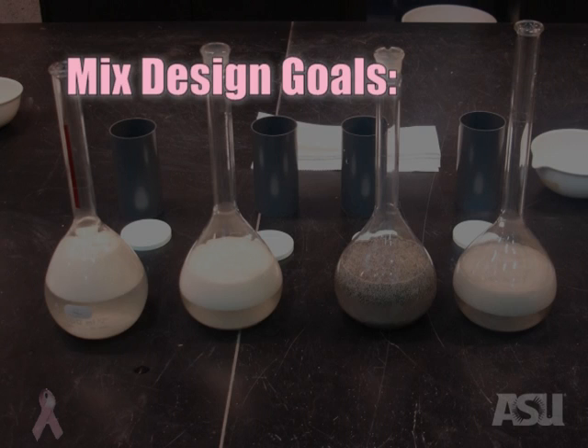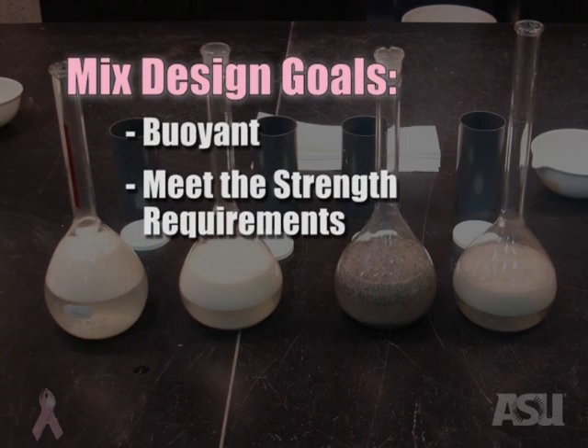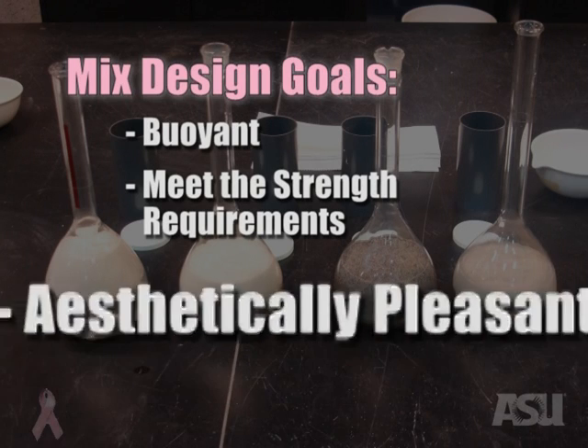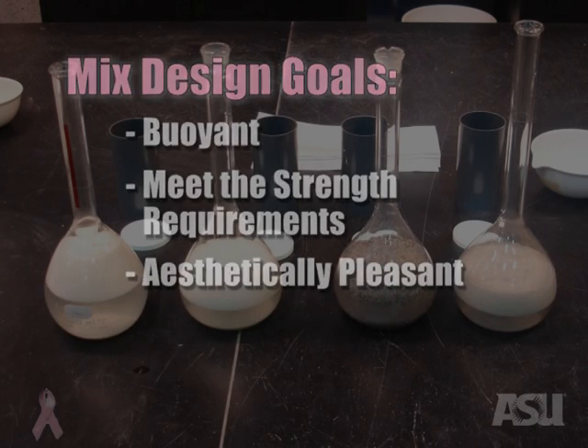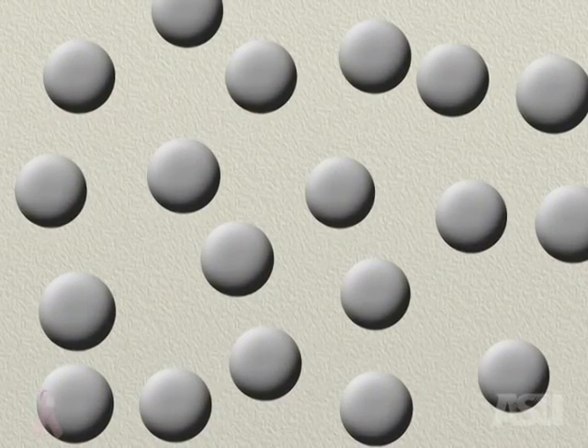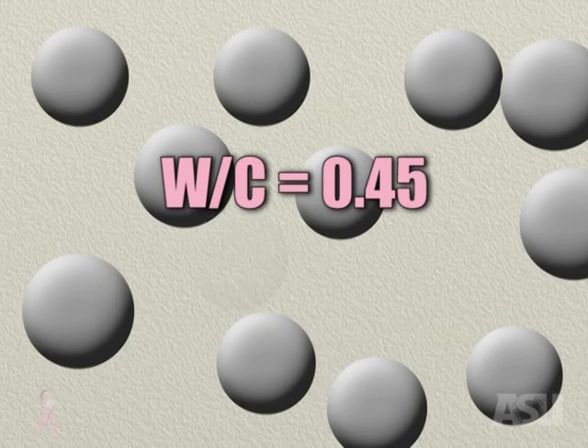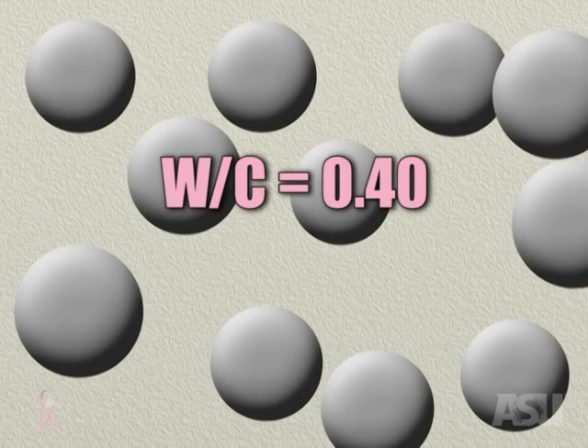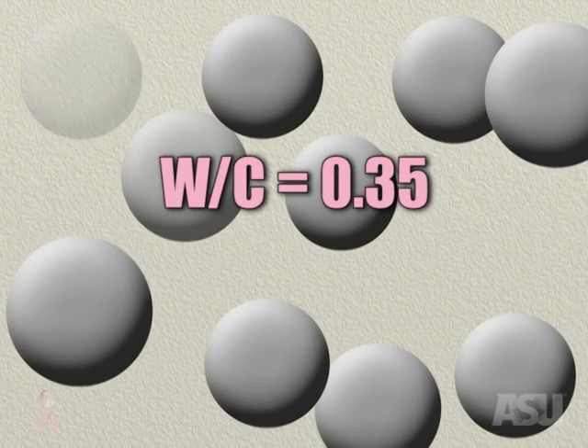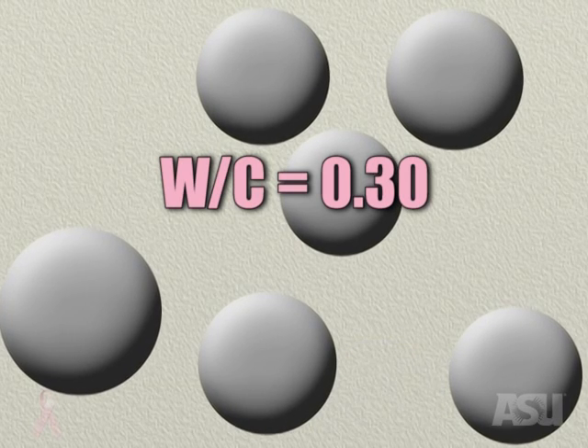The main goals for the mix design were to provide a concrete that would be buoyant, it would meet the strength requirements found by the structural analysis, and it would be aesthetically pleasant. To begin, increasing the particle size decreases the surface area that needs to be covered by the cement paste. This in part reduces water demand, yielding a lower water-to-cement ratio of 0.35, ultimately increasing strength.